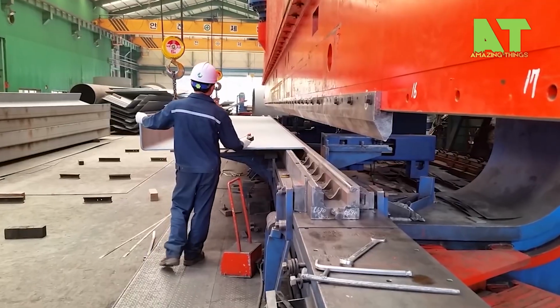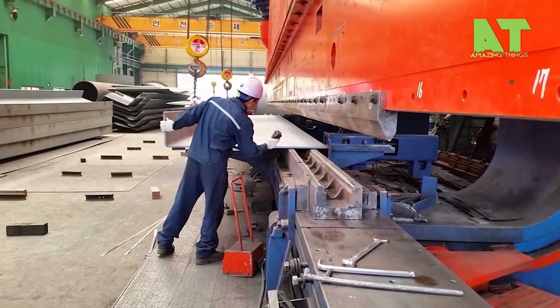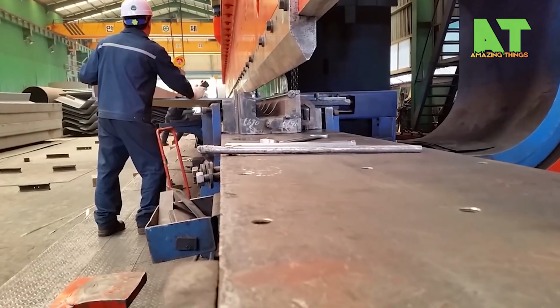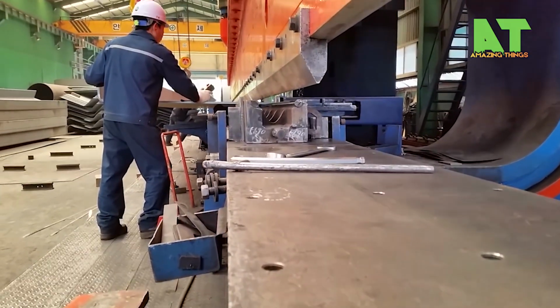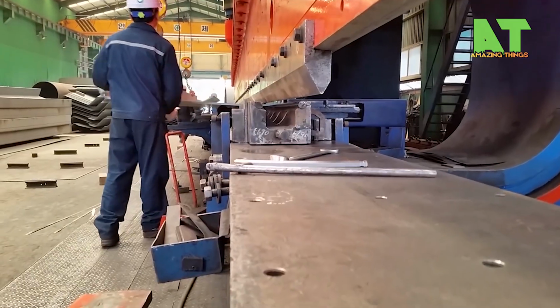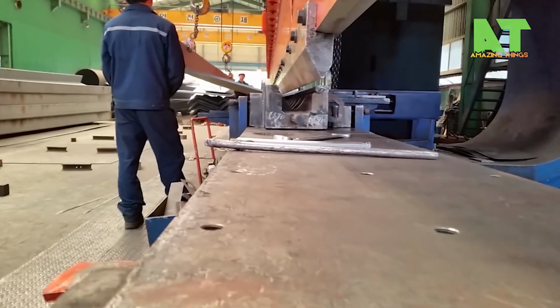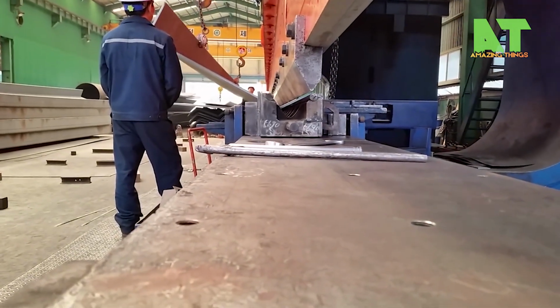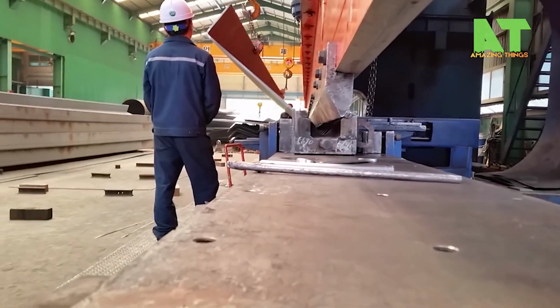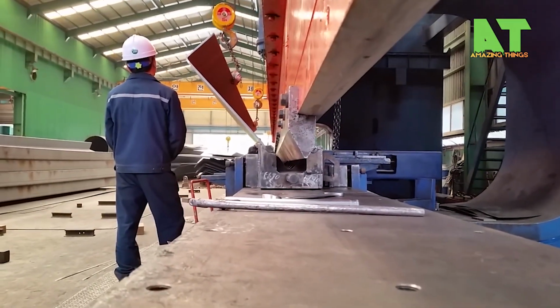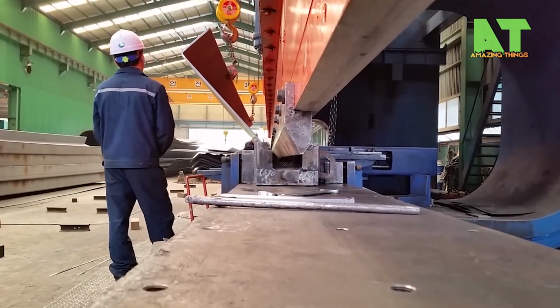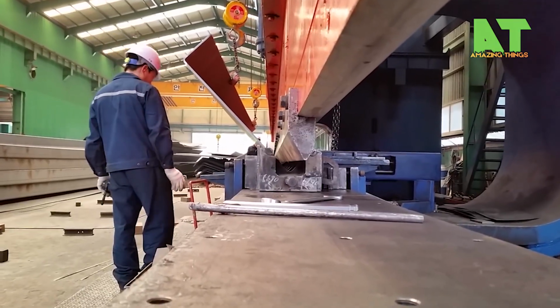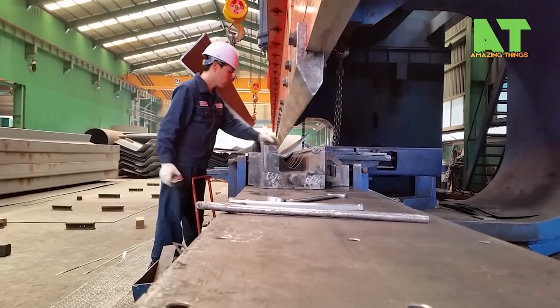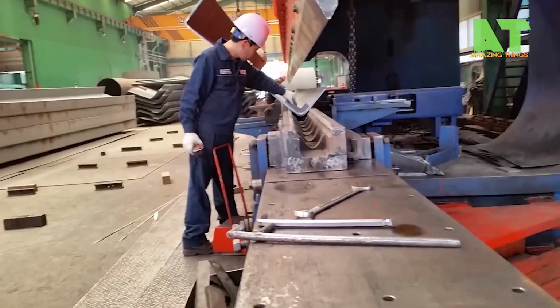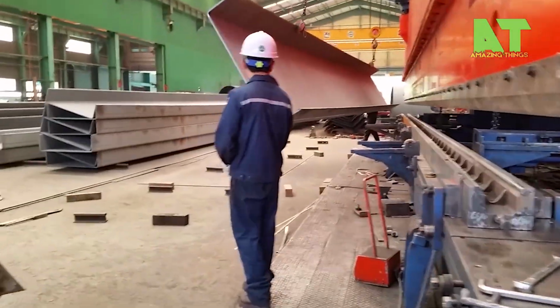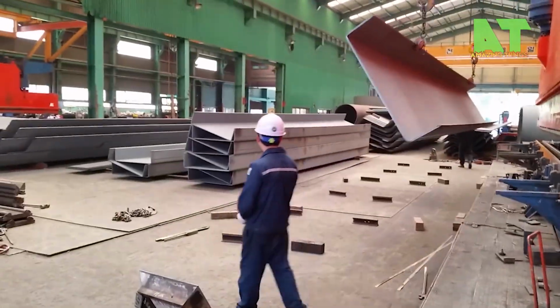At this tonnage, there's tremendous stored energy in the hydraulic system, and everything is controlled with precision. The CNC back gauge you see positioning the plate is accurate to within a fraction of a millimeter across that entire 20-meter length. The tooling is equally impressive. Those aren't standard dies. They're massive steel forgings, precision ground, and often segmented, so different sections can be used for different bend configurations. For thick material, the dies might be heated to reduce spring back and achieve more accurate angles.